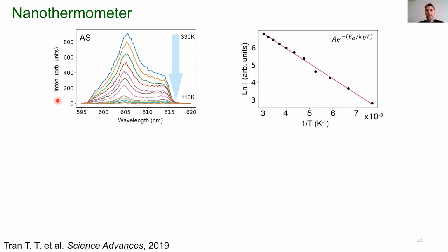What I like about this measurement is that if you plot it on a logarithmic scale axis, you can clearly see this Arrhenius type behavior, where it clearly shows the exponential dependence on temperature. Now, in this graph, there are no error bars, because the error bars are basically as big as the data point. And what I also like about this measurement is that when you have an Arrhenius type graph, most of the time people fit both the amplitude and the activation energy.